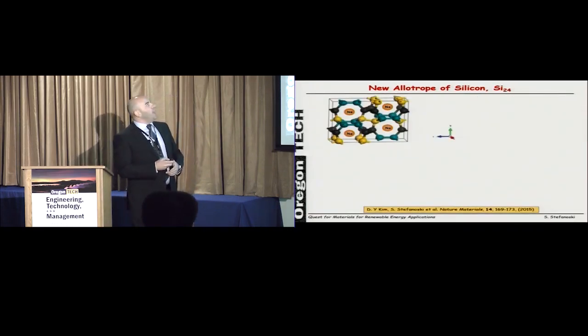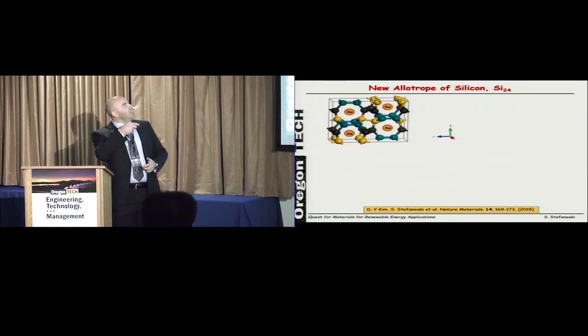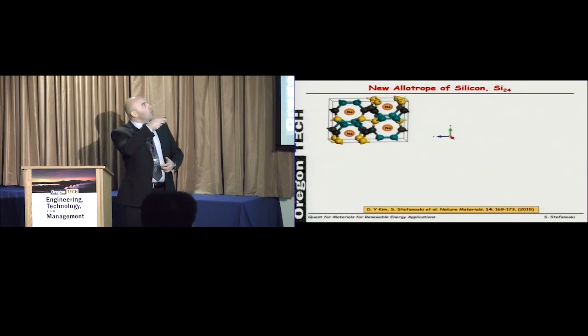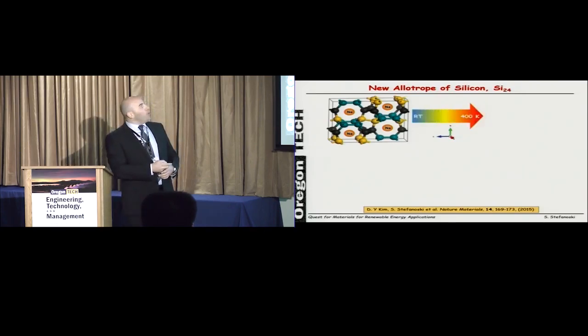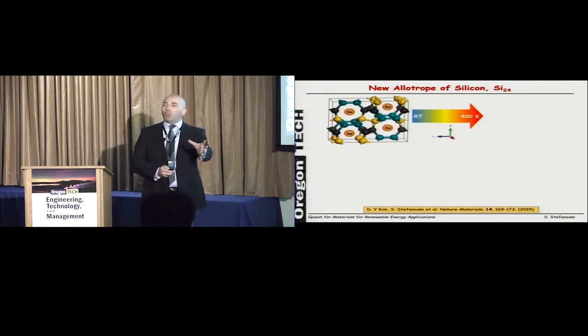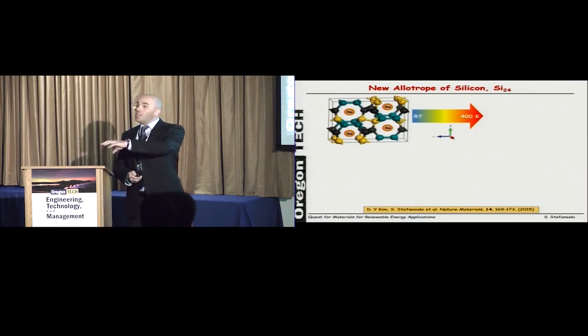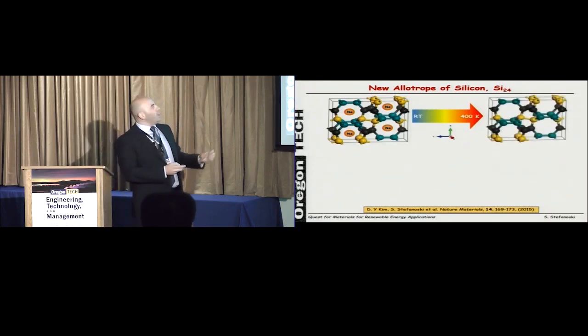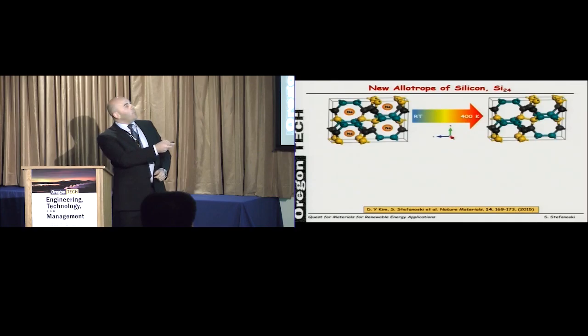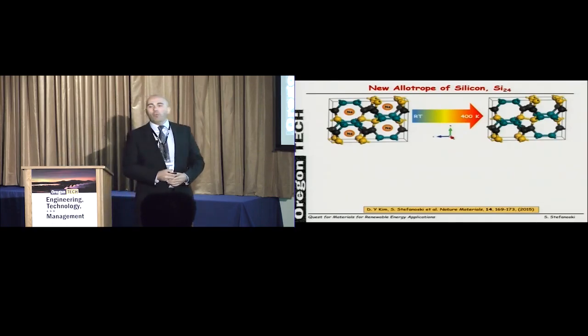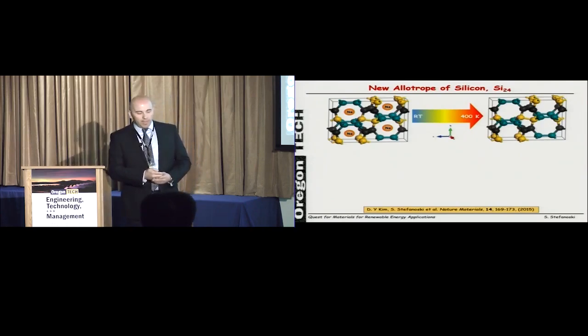When I say miracle, that is we have obtained this material, which is a combination of sodium atoms filling these linear empty chains built by silicon atoms. And if we bring this material to a temperature of about 400 Kelvin, because of the volatility of sodium and its high vapor pressure, we can completely remove it and end up with an exclusively silicon framework that we call silicon 24 due to stoichiometry considerations.